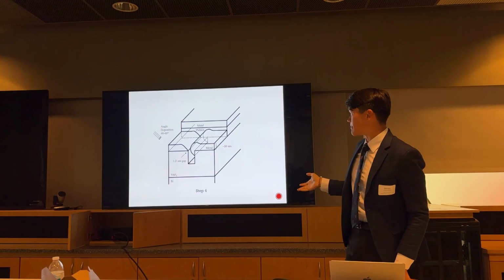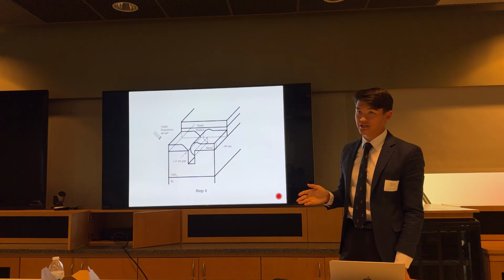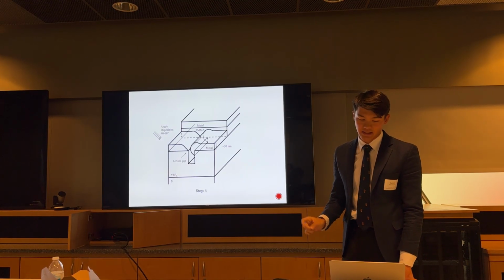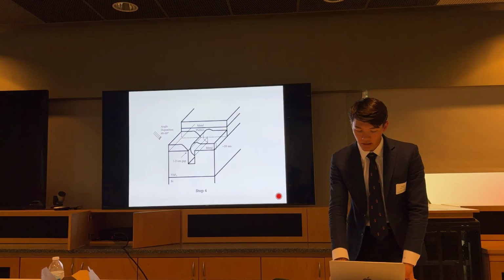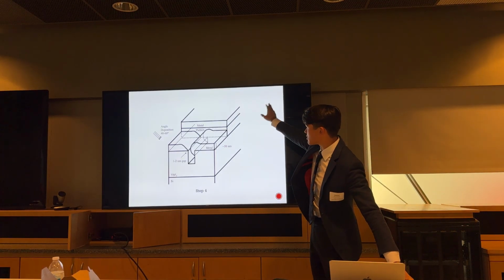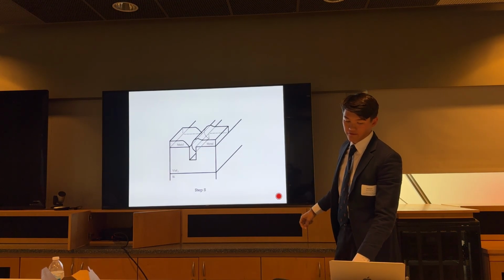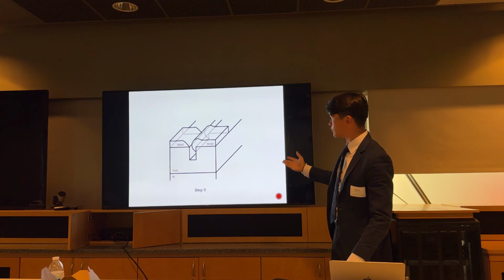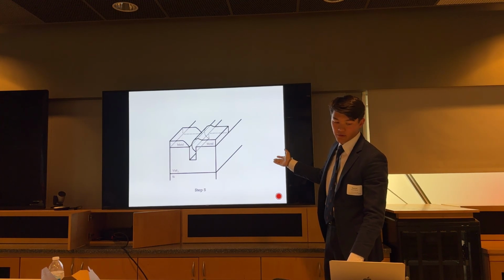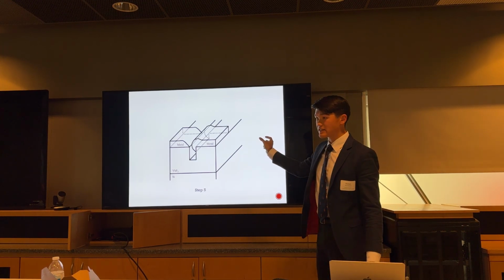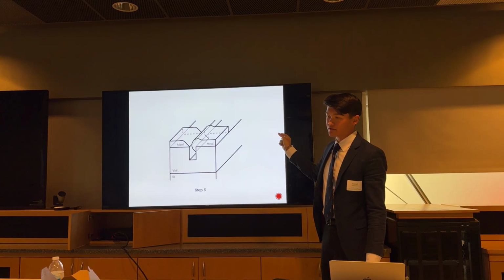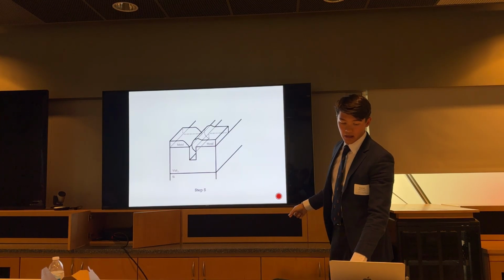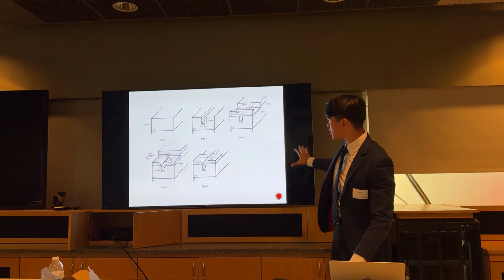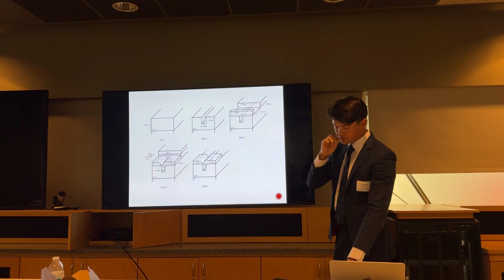So the rate of the deposition and the timing of the deposition matters a lot in terms of achieving that gap that we need for tunneling. Lastly, this additional metal on top of the PMMA is not needed, so a lift-off step is used to remove that, and we are left with the device that we want. However, all of this is still at a nanometer scale, and it's very difficult to create electrical measurements. So here's the overall summary step by step.